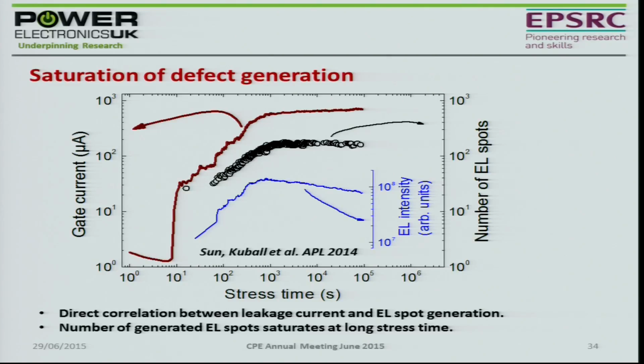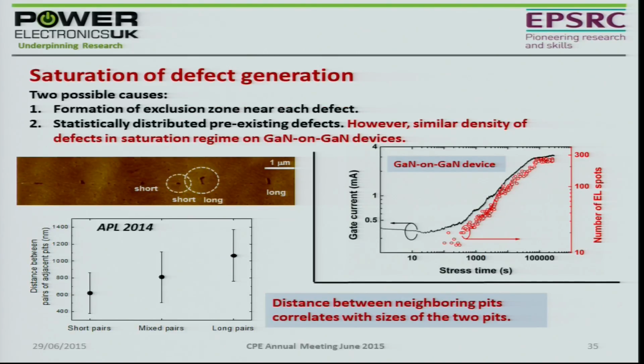This is a count of the number of defects, those little red blobs, increasing with time as well. You can see they all increase. They're all linked to each other. These defects are being produced, and they're producing light, and they're also producing gate leakage current. So what happens is these defects get to a certain size, and then they saturate. They don't get any bigger, but you get more and more of them developing along the gate interface with time. So the distance between these pits gets closer as time goes by.